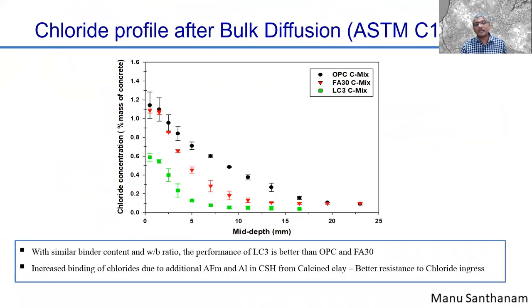Now, as far as chloride penetration characteristics are concerned, the direct bulk diffusion test, which is the true test for determination of chloride penetration, clearly shows that the amount of chlorides penetrating LC3 systems is much lower as compared to the fly ash systems, which is again much lower as compared to the cement systems, ordinary Portland cement systems. So definitely there are significant advantages of utilizing LC3 in concrete with respect to chloride diffusion characteristics.